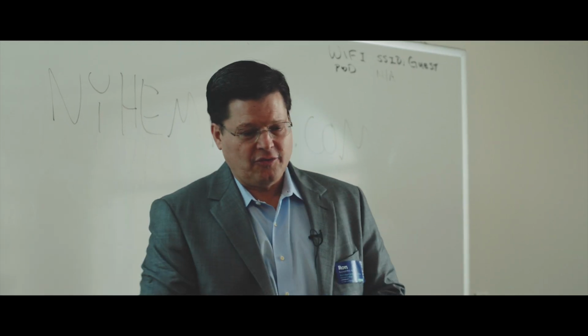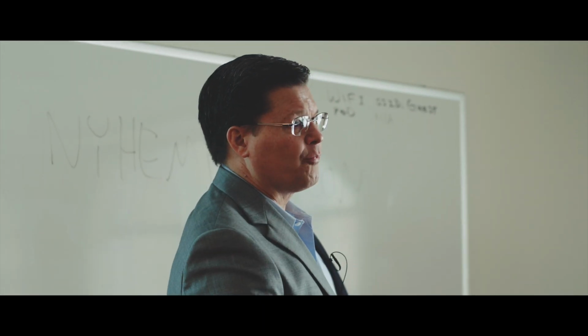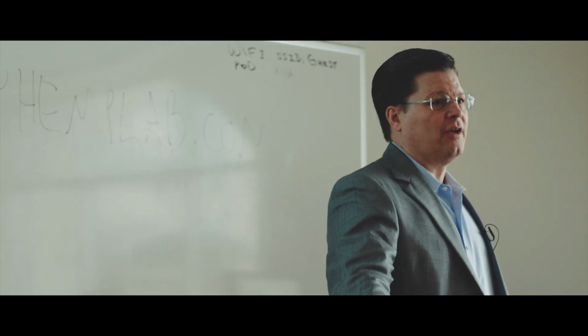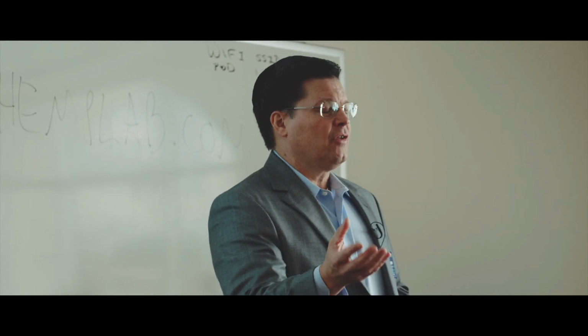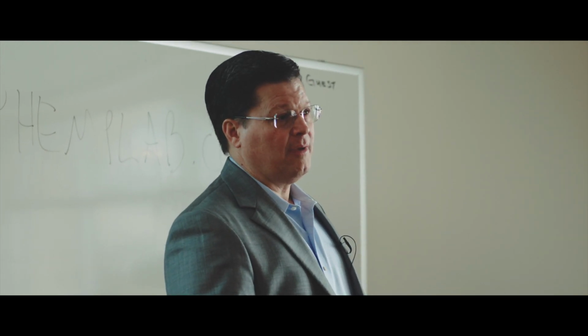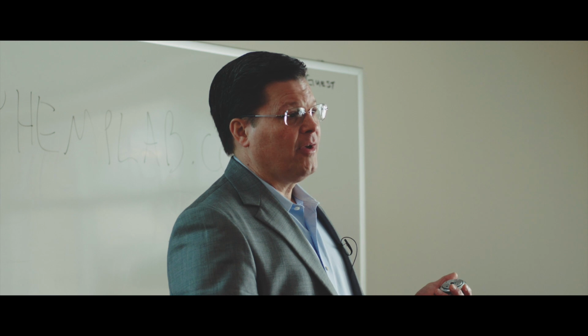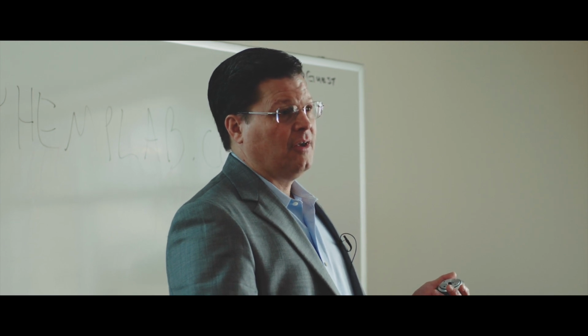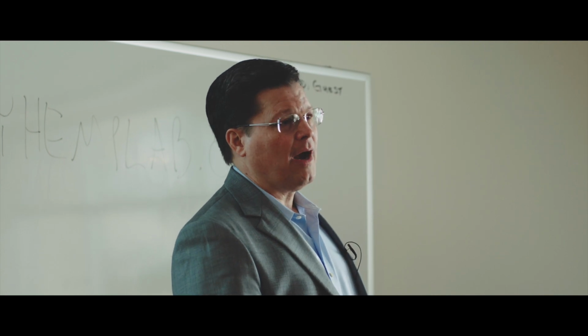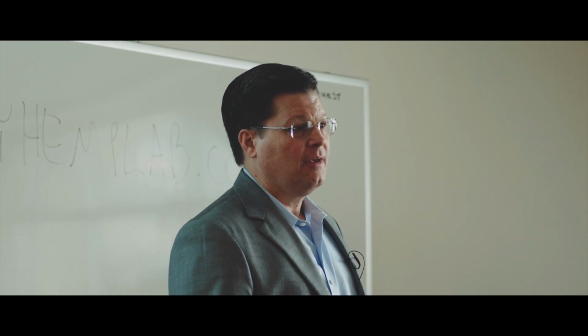They also have a product, so you see these tables, they have this kind of press board on them. And that's just glue and wood chips. Well, the glue is the unsustainable part. So instead of glue, they're using mycelium and they press it. And the advantage of that is this has to be treated so that it meets fire code. Mycelium doesn't combust until about 900 degrees. So it's naturally fire retardant. It's naturally hydrophobic. It resists water. Okay, so it has really great properties, so they can compete in that space.